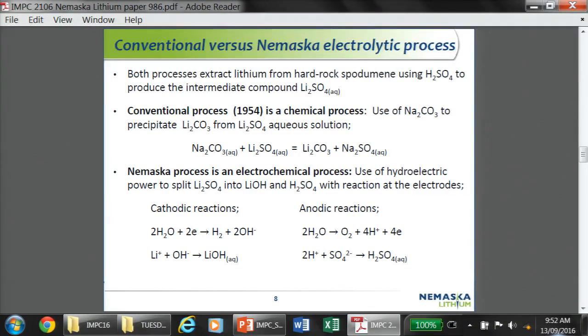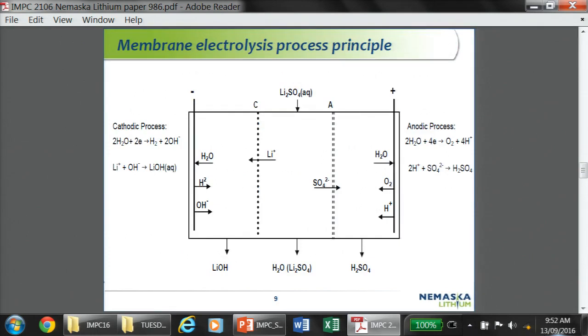So basically, you use hydroelectric power to split the lithium sulfate into lithium hydroxide and sulfuric acid. You can see that as an electromembrane process with a decomposition of water at the electrode, forming hydroxide on the cathodic side and sulfuric acid on the anodic side.